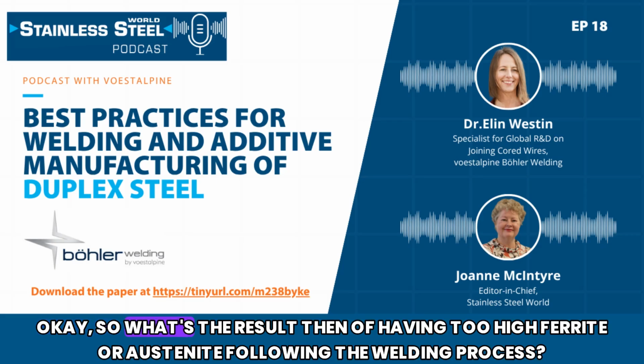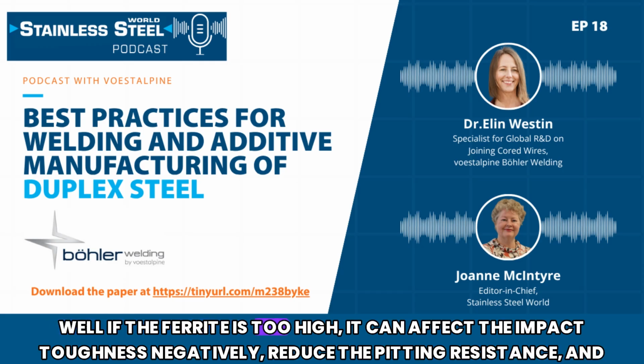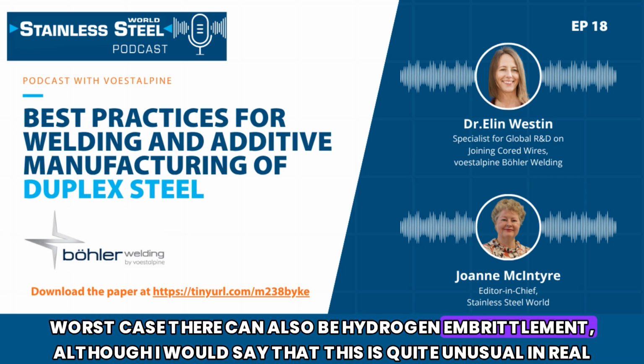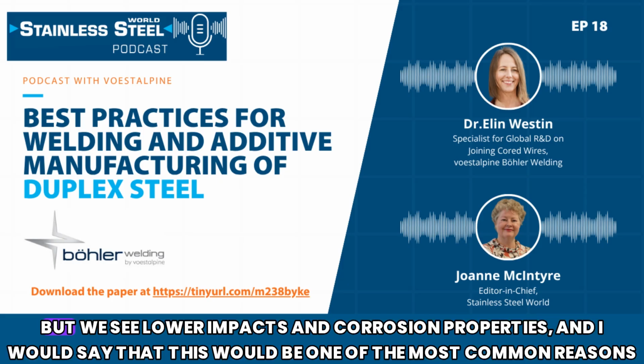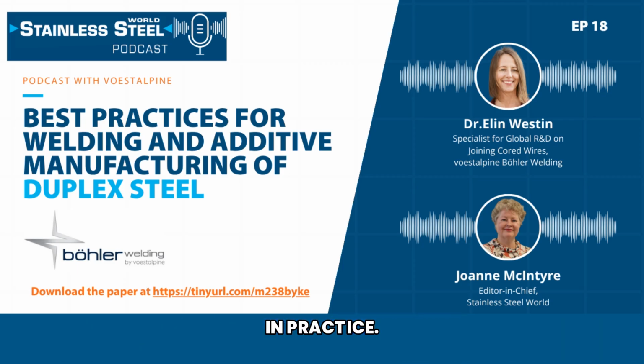Okay, so what's the result then of having too high ferrite or austenite following the welding process? Well, if the ferrite is too high, it can affect the impact toughness negatively, reduce the pitting resistance, and in worst case, there can also be hydrogen embrittlement, although I would say that this is quite unusual in real life. But we see lower impacts and corrosion properties, and I would say that this would be one of the most common reasons for having corrosion issues in practice.